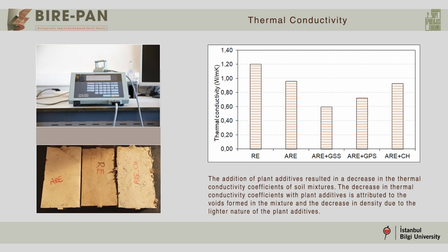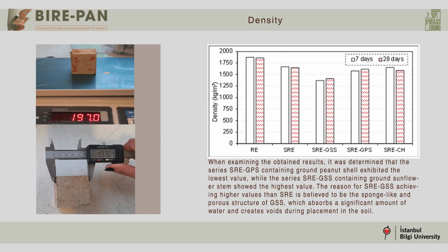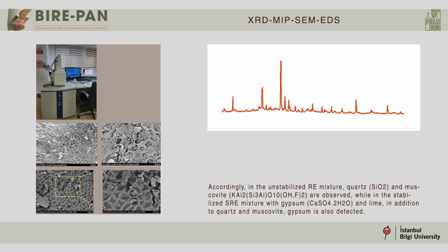Thermal conductivity value decreased with the plant additive mixture, with the highest decrease in GSS and lowest decrease in corn husks. When we add plant additives, the highest decrease is in GSS and lowest decrease in corn husks. And also we observe, with the Alker recipe, quartz and muscovite.